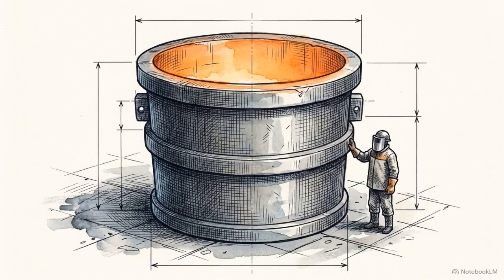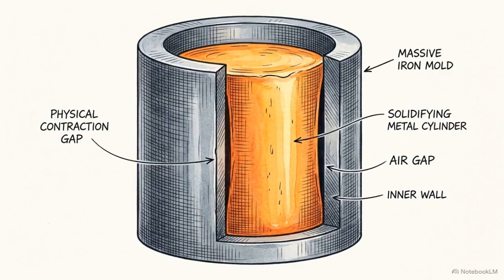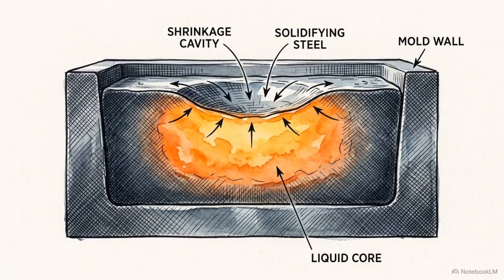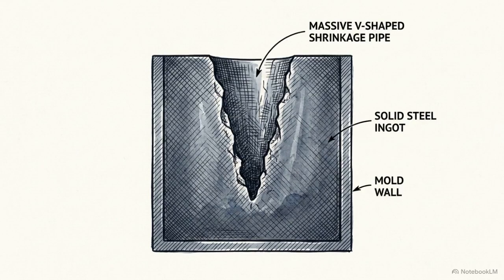Zoom out from the microscope, and you encounter a massive physical threat caused by the freezing process itself. Liquid metal is less dense than solid metal, so as it freezes, it physically contracts. The outer shell of a casting cools and freezes first, trapping liquid metal inside. As that trapped core eventually turns solid and shrinks, there is no extra liquid to fill the gap, tearing open a massive physical void in the center, known as a shrinkage pipe.